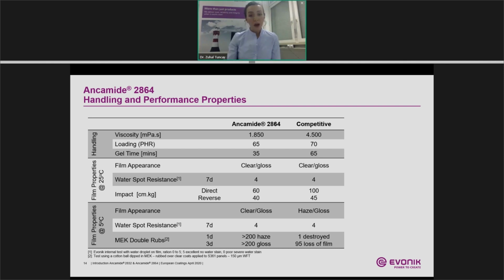With the competitive system, after 1 day, the coating was completely destroyed as soon as an MEK swab was placed on the coating. And this highlights the poor film integrity of the competitive system, which may dry to touch after 1 day, but there's no sufficient cross-linking as the coating provides no chemical resistance. And after 3 days, there is some improvement, but even then, the MEK double rub is still less than 100 units.